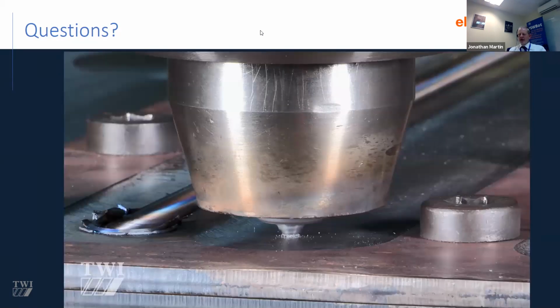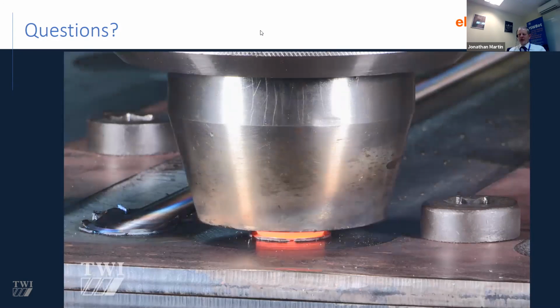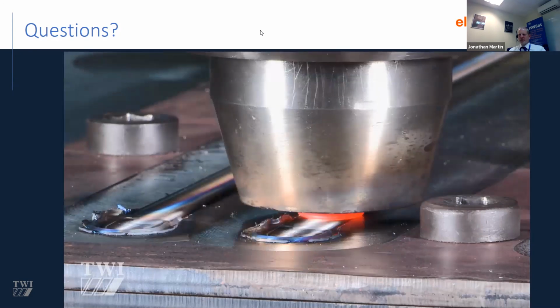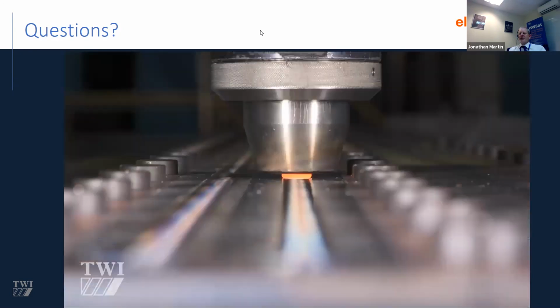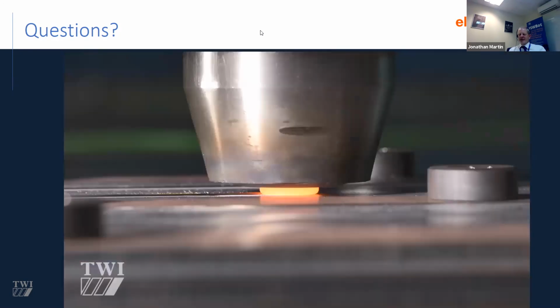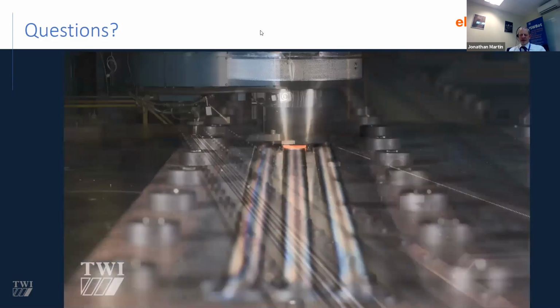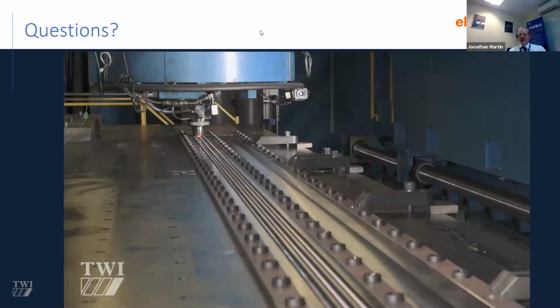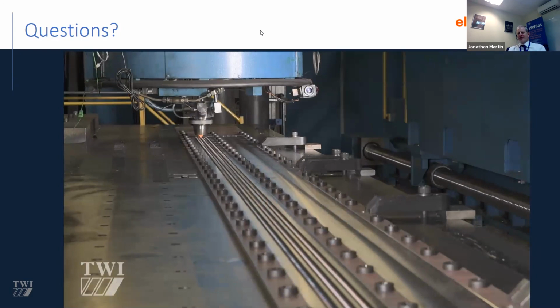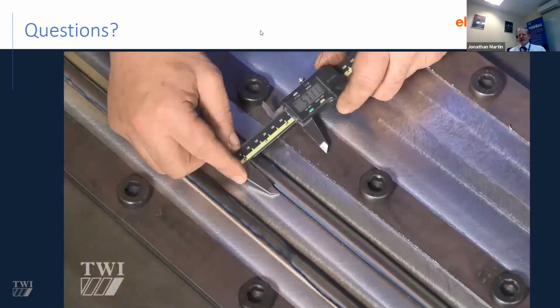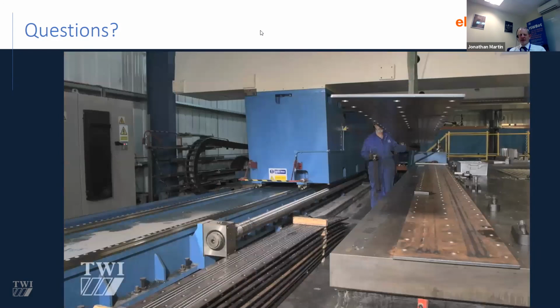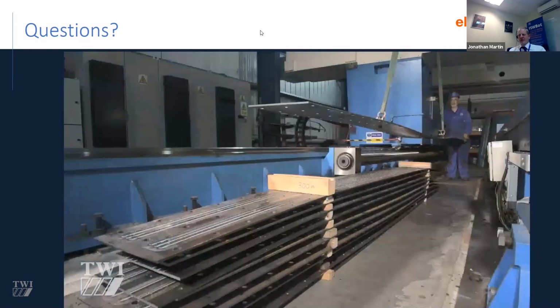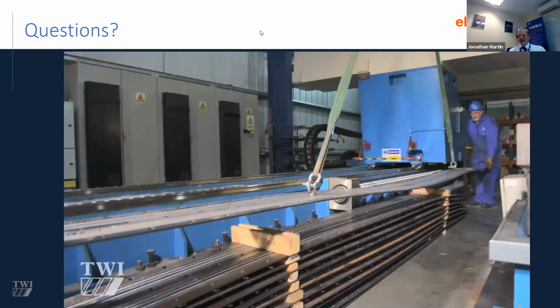Okay. Yes, there is a small pilot hole that we use in order to plunge the tool into. This was mainly to stop the material coming out of the workpiece causing problems with the tool. We think that perhaps we can eliminate the need for the pilot hole, but we didn't want to change the tool design at the time, so we drilled a very small diameter pilot hole that the tool then plunged into. So each of these 40-meter welds, there were 8 plunges and 8 5-meter long welds.